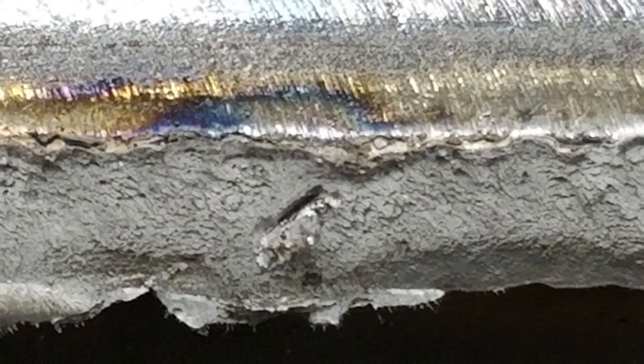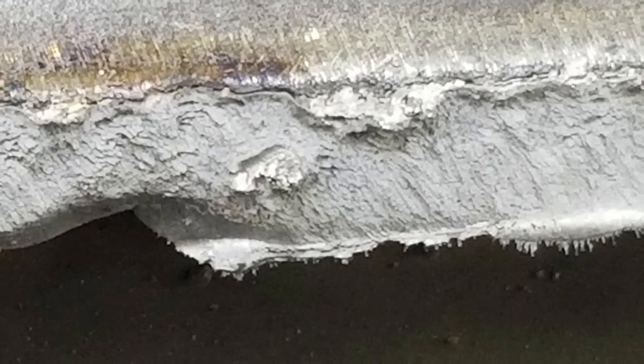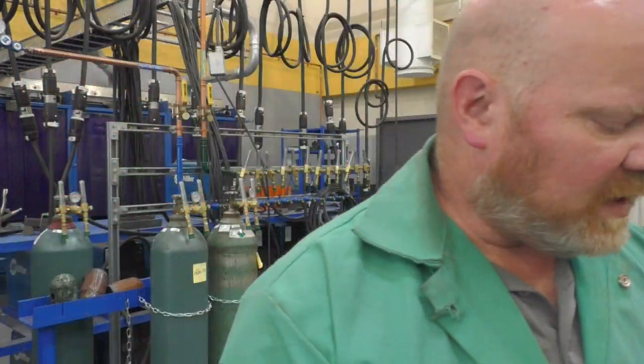I mean, it is short arc. It takes a second for it to get up to temperature. And this is on 3/8 material, okay? So I do have bad spots in my restarts. I have some holes right there. Those are areas of non-fusion, and those areas of non-fusion over time with vibration, anything under any type of cyclical loading, could cause cracks to propagate down the road.